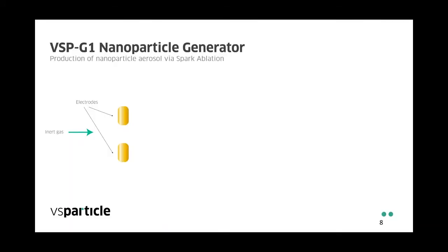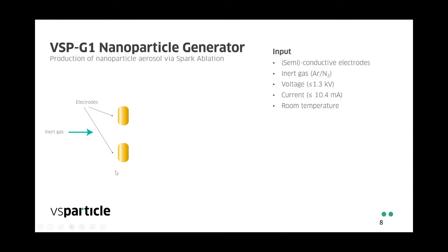Our G1 nanoparticle generator uses spark ablation to prepare nanoparticles. What you need for that are two electrodes made of a semiconductive or conductive material, such as a metal, and an inert gas, such as argon or nitrogen, which takes the nanoparticles away from the electrodes and brings them downstream. A voltage is applied between the two electrodes, and the entire process can run at room temperature.